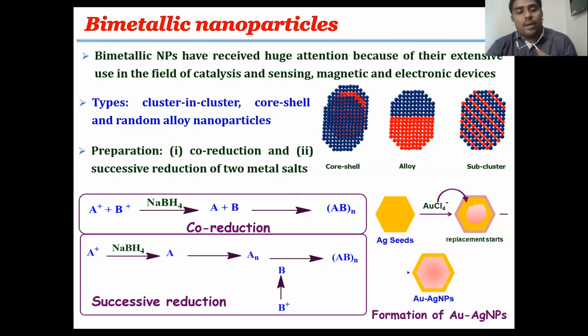Generally, bimetallic nanoparticles are prepared by two strategies. One is co-reduction and the other is successive reduction of the two metals. In co-reduction, which is the easiest one, two metal precursors are taken, and with the help of a reducing agent as well as the autocatalytic mechanism, the bimetallic nanoparticles are prepared. And in the case of successive reduction, one metal is formed first, after that the other one.